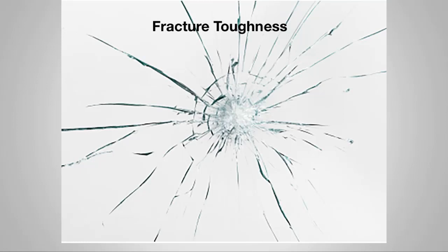So fracture toughness, probably the best way to think about it, and a lot of people have used this analogy, is to think about having a crack in the windshield of your car. So the force that it takes to propagate that crack further is going to be fracture toughness. So we see little porosities or imperfections in zirconia all the time. How much force will it take to propagate a crack through that zirconia is what fracture toughness really is. So flexural strength, maybe not as an accurate determination of true strength, but fracture toughness is more in line to what I think we should be thinking about.